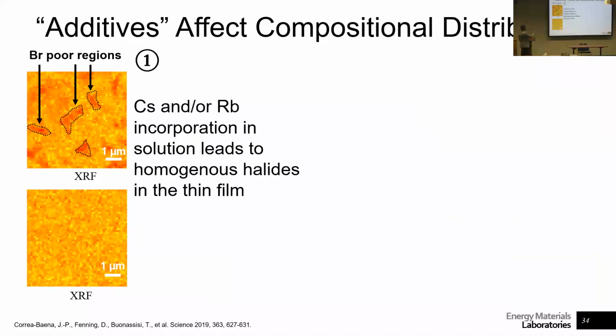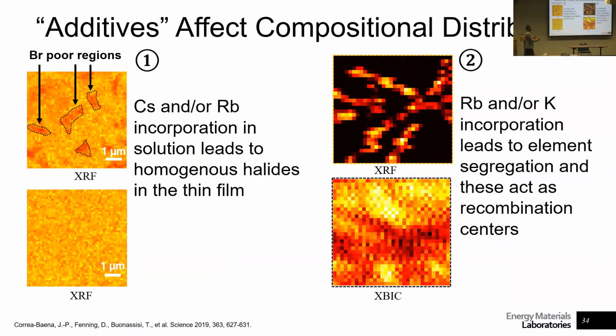This allows us to look at chemical maps like this. Here we have bromine poor regions, for example, versus a homogeneous film. So that's the chemistry. But if we want to do compositional analysis of how that is affecting current, we can see here, for example, how rubidium clusters affect the current of our device. This is low current that is being tied to those rubidium heavy atoms. So areas where we have a lot of rubidium have lower current, and this allows us to say, okay, rubidium is a bad element to have in our solar cell. We're basically doing these correlative studies on what elements are good and what elements are bad for a solar cell.